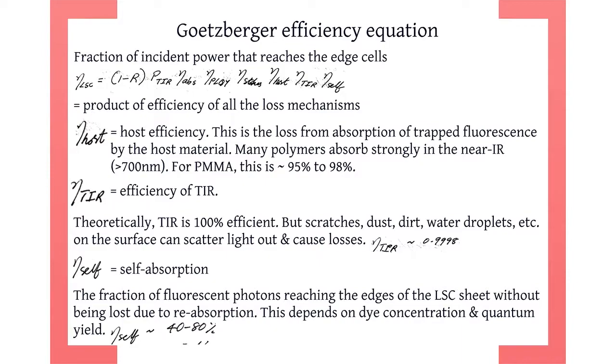Now, if you multiply all these efficiencies out, you'll get a number which is probably less than 10%. The world record, at least a few years ago, was about 10 to 12%. That is by stacking 3 different layers, like a multi-junction solar cell. So it's pretty low. That's why it's still a technology in flux, quite immature, but still a lot of work and very interesting applications.